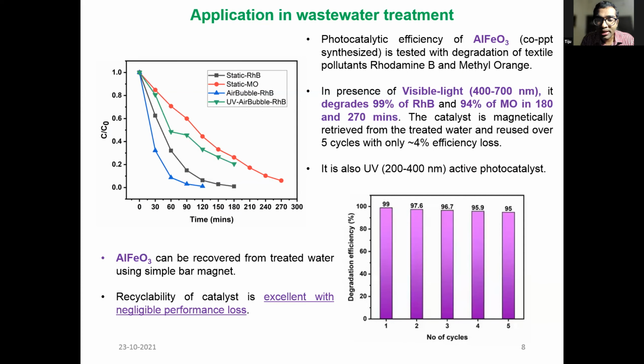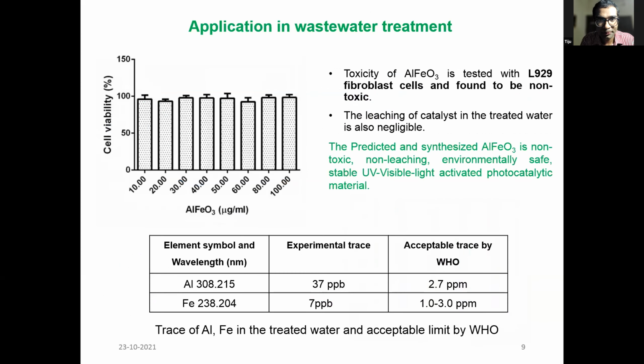Most of the degradation efficiency decline that you see with respect to the number of cycles is entirely attributable to the retrieval efficiency. The particle as such behaves in terms of its recyclability better than TiO2. Next, please. So that is not it alone.